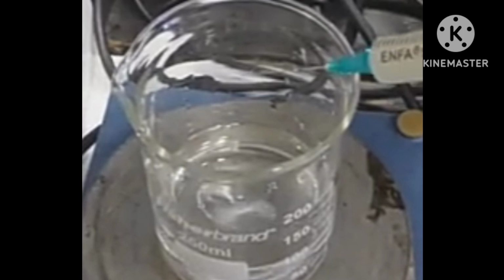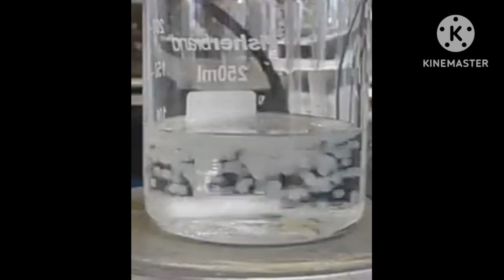The healing agent was to be encapsulated within the coating to provide self-healing ability. When the paint experiences microcracks or small damages, the capsules containing the healing agent will rupture, releasing the healing material into the damaged area. Once released, the healing agents flood into the damaged area and react to fill and seal the defects. By undergoing the process of reversible chemistry, the healing material can regain its structural integrity, effectively repairing the damaged coating.